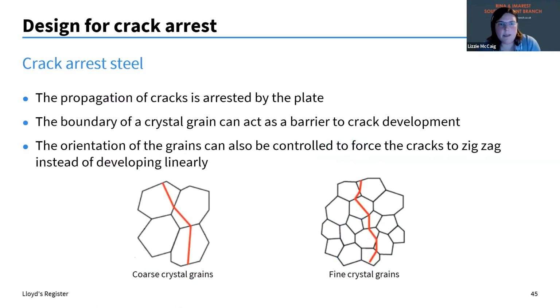Now, the way crack arrest steel generally works is, as I said, you arrest the propagation of cracks using the plate itself. And you can use the boundary of the crystal grain to act as a barrier to crack development. If you remember, I said before that one of the problems for the Liberty ships was they had quite coarse crystal grains in their plate. If you have coarse crystal grains, it means you have fewer crystal grains in the plate, which means you have fewer boundaries that could slow the crack down and halt it. Whereas if you have fine crystal grains, you've got a lot more boundaries, and the path the crack takes has got to go through there and there and there. And this can arrest the crack. You can also use the orientation of the grains to force the cracks to zigzag instead of developing linearly, which again can slow the crack down and ultimately halt it.